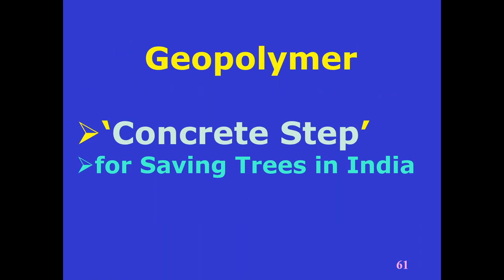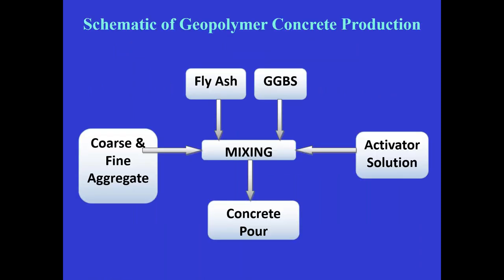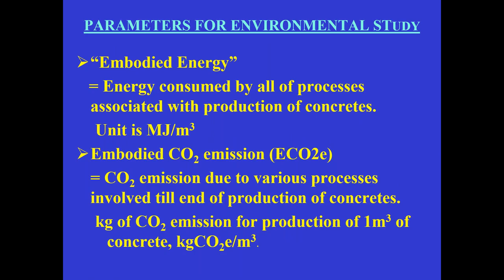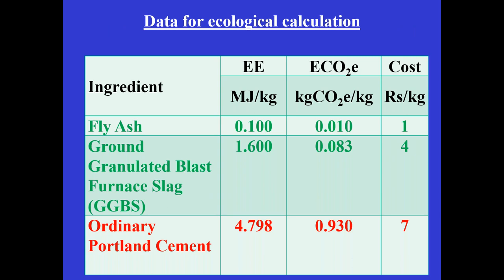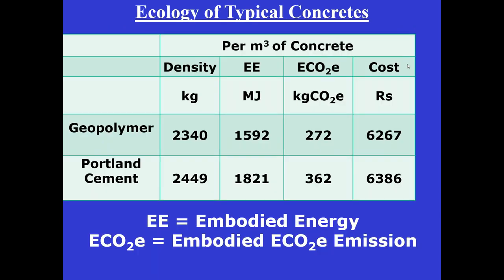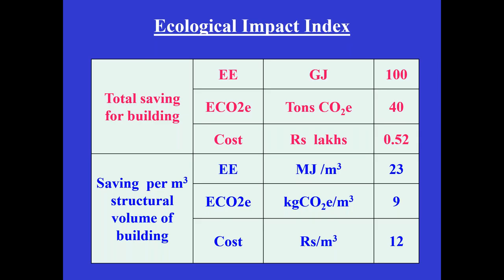So this I have already told you, and we can do the embodied energy and carbon dioxide emission calculations. We found that for one typical formulation, you can see here that embodied energy is reduced in geopolymer and the carbon dioxide emission is reduced. Cost is not much changed. This building was analyzed and proved how much saving there is with geopolymer. This number is available.